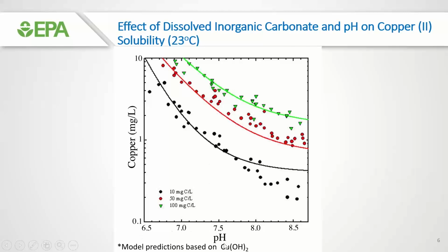And then again, this is the new copper situation, the cupric hydroxide situation, our worst case. So it's good to model the worst case, and that's relevant as well. But they match up pretty nicely. So certainly it shows here this sensitivity to pH, which I think most of us understand, that higher copper levels are going to be associated with lower pHs. And of course, it points out too this effect of the DIC, the dissolved inorganic carbon concentration. As you increase your DIC from 10 to 50 to 100, copper levels go up quite a bit. And this is really important as well.